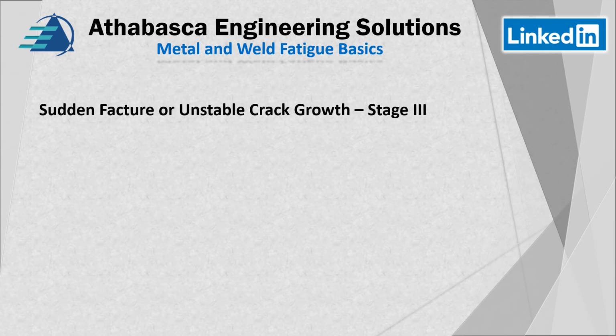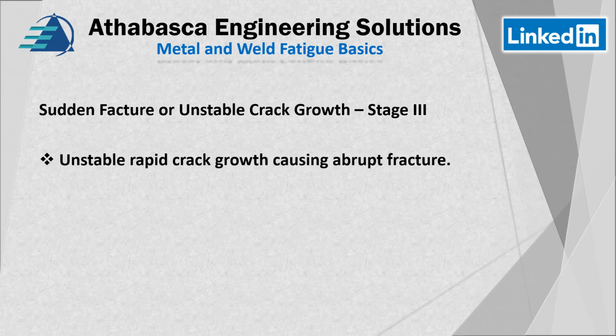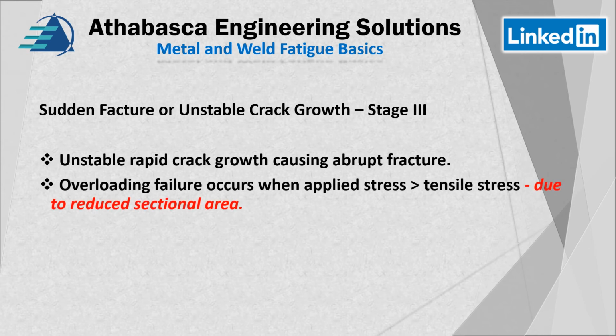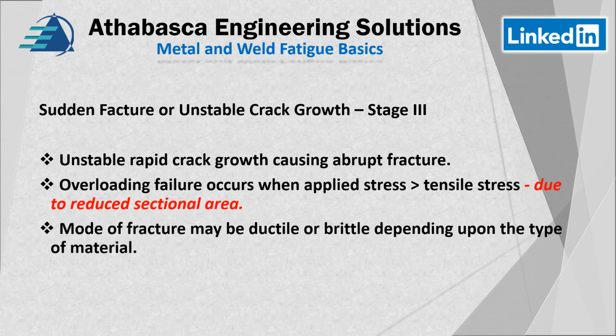So we got this unstable fracture. It's characterized by a catastrophic failure. So it's unstable crack growth, which causes abrupt fracture. Basically, it's an overloading event that occurs when the applied stress exceeds the tensile stress due to a reduction in area, because the crack across the cross section of that part will decrease the cross-sectional area, and of course the tensile stress is the force divided by the area of the part. So if the cross-sectional area is reduced because the crack grows, there's less area left to carry the stress. So as the crack grows, the stress grows. And that's basically the mechanism for what happens.